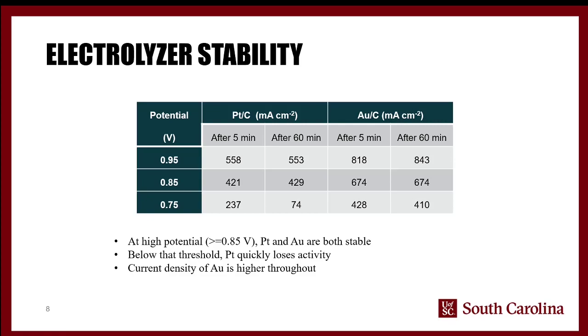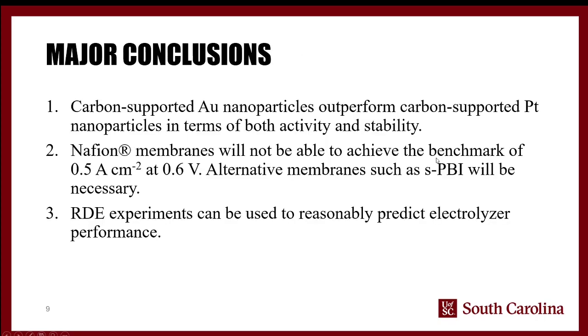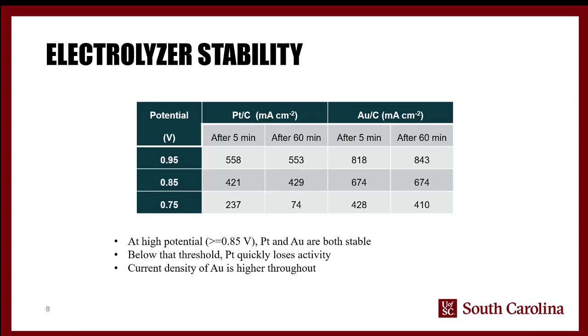Stability, of course, is another key point here. You can have the best catalyst in the world, but if it doesn't last more than 5 seconds, it's not very useful to you. And so what we find is that with platinum and gold, if you're above 0.85 volts, you actually get good stability from both of them. Over the course of an hour, they both basically maintain their activity. Gold actually even went up a little bit. But you can see here at 0.95, at the same potential, gold has much higher current density. And the same holds true as you go down to 0.85 and 0.75.